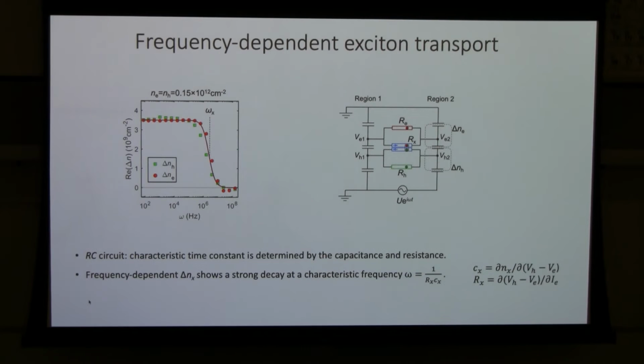So those measurements happen at a single frequency. What we can also see is, when we modulate the system at different frequencies, how would the electron and hole response actually change? Here we show the electron current and hole current in the exciton region. What you can see is their responses are identical at all frequencies. That means the electrons and holes are really moving together dynamically. And both of them show a characteristic decrease in frequency at about 1 megahertz.